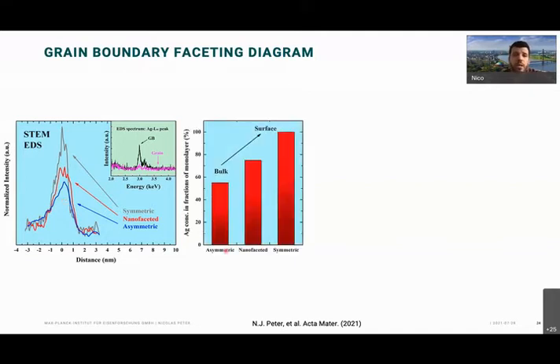So we preferred to collapse this and then talk about fractions of a monolayer, because we know for a monolayer, we have our very surface case, that's a monolayer of silver more or less. And from that, we know the concentration and relate all the other intensities that we found. So in this, we could see an increase of silver in terms of monolayer concentration at the boundary. And I think this makes much more sense in this case.